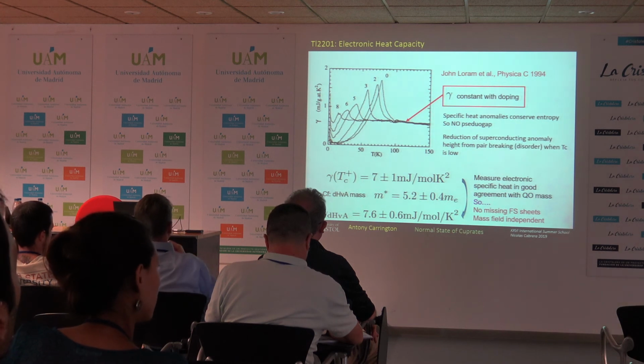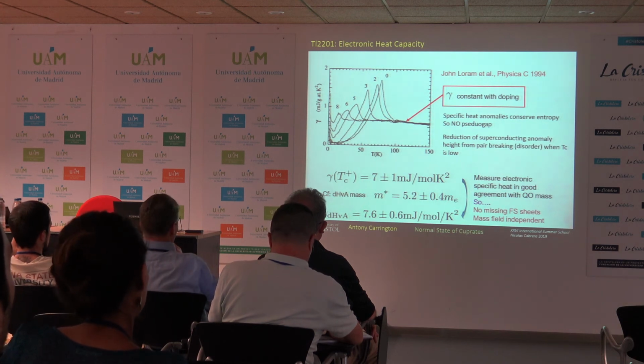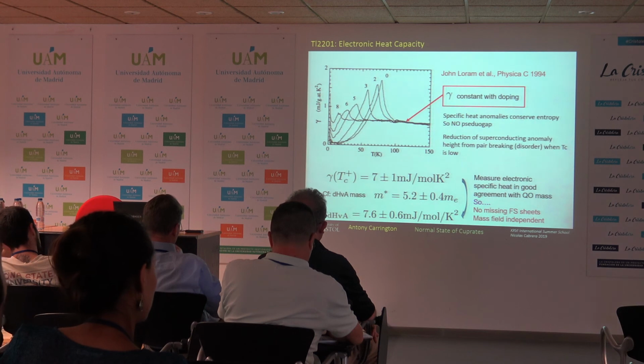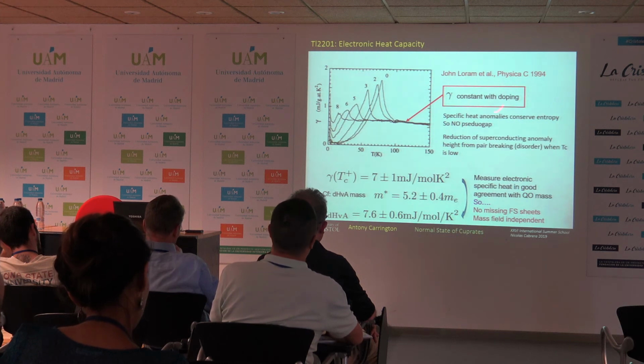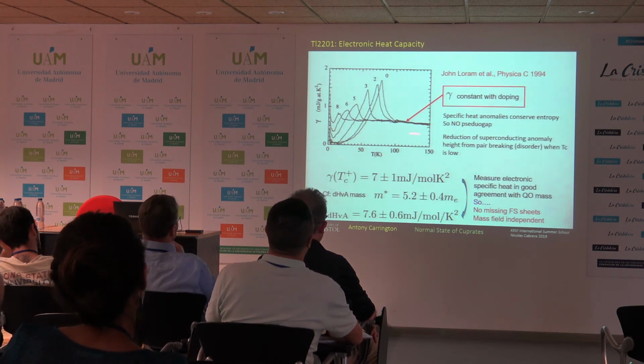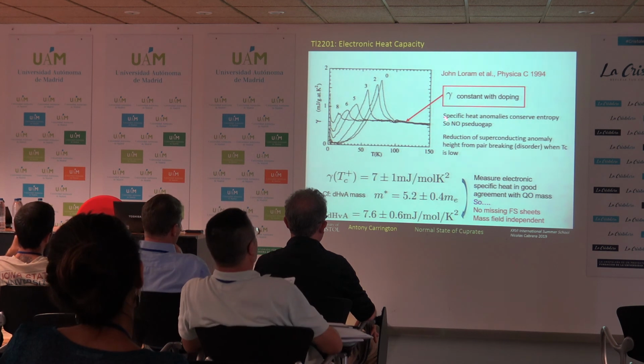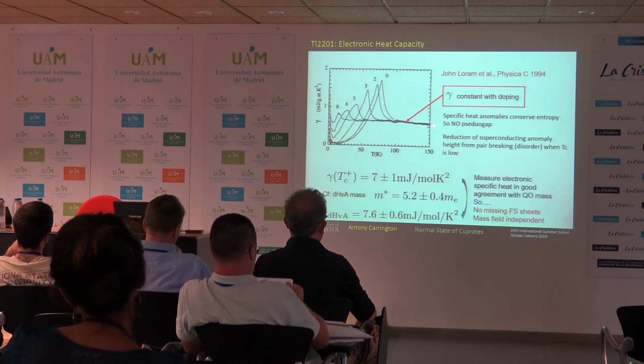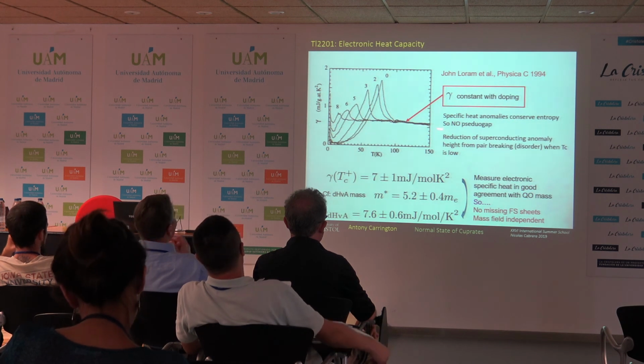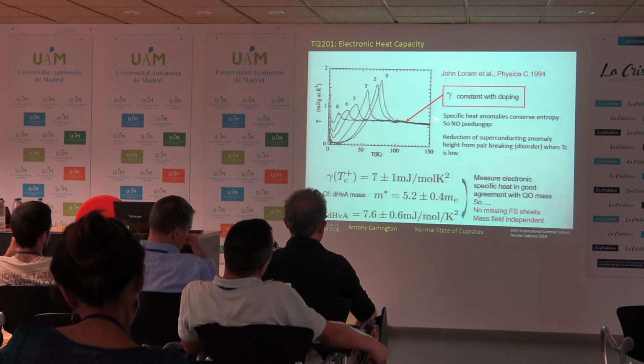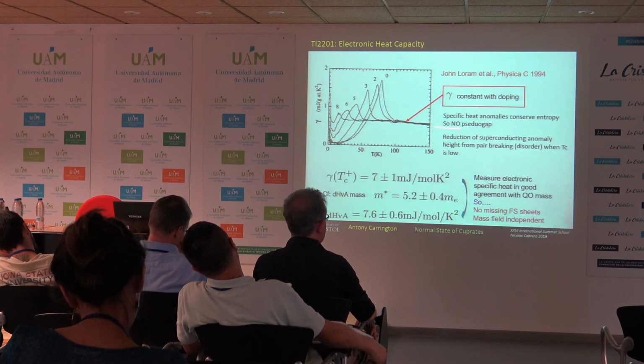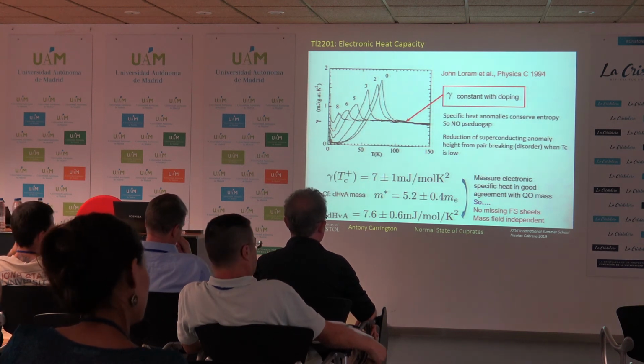Okay, so I'll flash up here some heat capacity data. There's been a lot of talk about quantum critical points in overdoped Cuprates, and this is a bit of data that nobody likes to show. And the reason is because this is data from John Loram. It shows overdoped thallium 2201, and what you can see here is that gamma, for all of these different TCs, is almost completely independent of doping. It doesn't change, right?